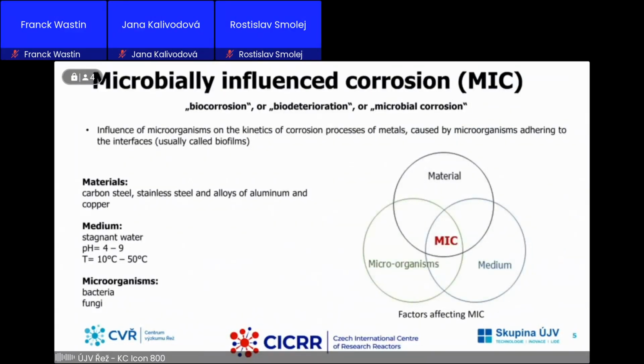Microbial corrosion, or microbial influenced corrosion, represents the influence of microorganisms on kinetic processes of metals caused by microorganisms adhering to the interface. Occurrence of microbial corrosion depends on the type of material, environmental conditions, and kind of active microorganisms. The most dangerous microbial corrosion is for carbon steel, stainless steel, and alloys of aluminum and copper under stagnant water, at pH between 4 and 9 and in a temperature range from 10 to 50 degrees Celsius. The kinds of active microorganisms are typically bacteria and fungi.